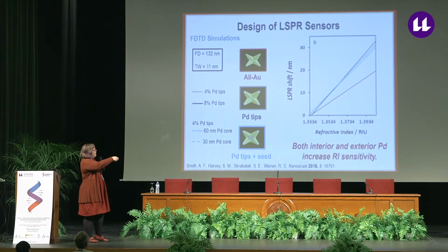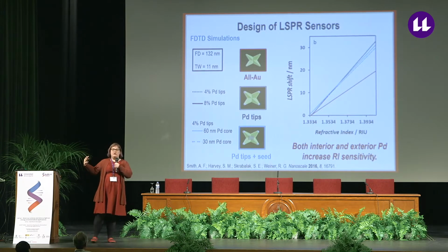And shown here are the results where we're looking at the shift in LSPR as a change of refractive index. And what we'll notice is that the red line corresponds to the all gold model, and it's the least sensitive to changes in the local environment. But having any little bit of palladium at the tips or in the interior increases the refractive index sensitivity.